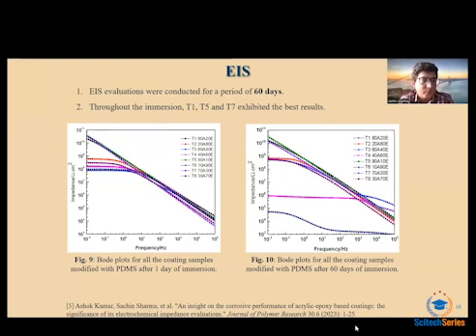So T5 exhibited the best results, and this coating formula was 90A10 epoxy. So the 90 to 10 ratio exhibited the best results, and T1, T5, and T7 showed a Z impedance value exceeding 10 to the power of 10 ohms centimeter squared. In other words, providing excellent barrier performance, okay, against the corrosion.